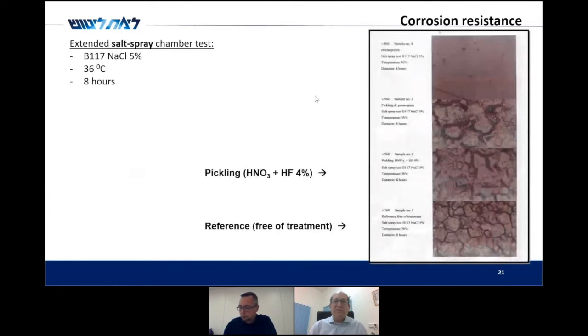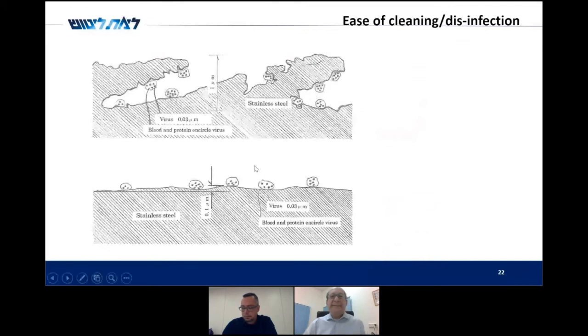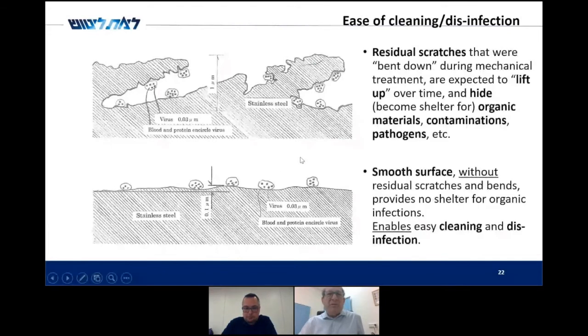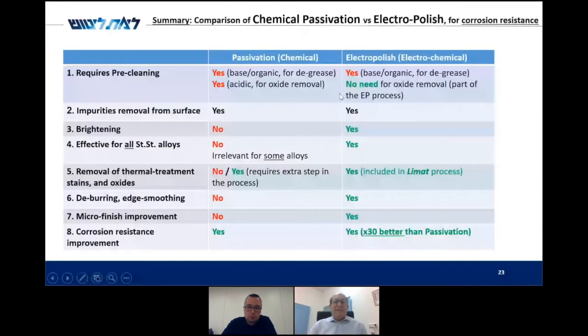I will not talk too much about this salt spray chamber test, and I will also skip a little bit about this cleaning or disinfection. We know that in normal or mechanical polishing, we have scratches that can be shelters for organic materials. In smooth cases like electro-polish, this does not happen. Unfortunately, I do not have time to go into the details, but when comparing passivation to electro-polish, we see that the corrosion resistance improvement is 30 times better than passivation when you use electro-polish. This is due to the depth.